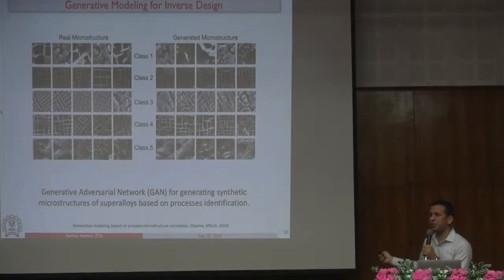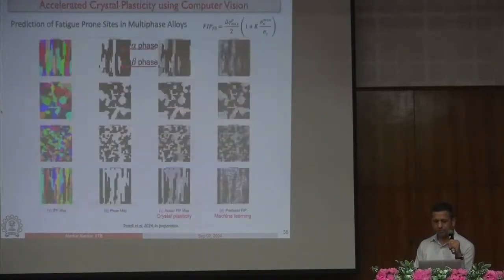And we actually applied multiple statistics measures. We did 2-point, we did some of the synthetic image processing based statistics, and the statistics of these generated microstructures is identical to the original. You will not see any microstructure which is identical individually to any of the used microstructures, which is absolutely fine. But the statistics here is the same. These are reliable for us, and we are using it for some of our work.